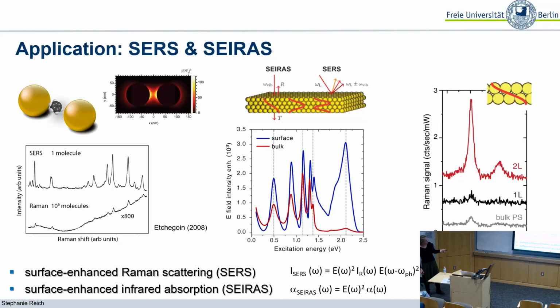So down here is a Raman spectrum of 10 to the 6 molecules, and it's increased by a factor of 800, and you can see some peaks. It's a rhodamine spectrum. And here is the same spectrum coming from a single molecule when it was placed in a really very strong plasmonic hotspot. So this amounts to 8 orders of magnitude increase in the scattering intensity, and people have the hope to use it for single molecule detection and so forth.